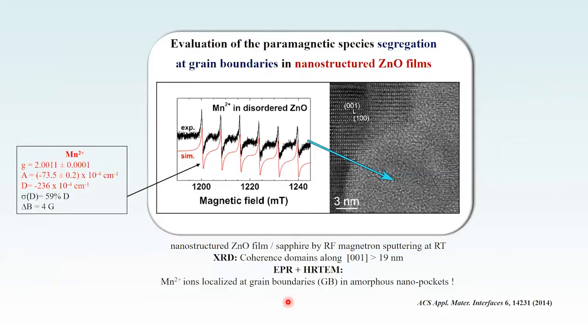This result was useful in investigating the properties of zinc oxide films. In an undoped film, we observe the presence of native manganese impurity ions at ppm concentration. From correlated EPR and high-resolution TEM, we concluded that the impurity ions were segregated in an amorphous environment. This is difficult to detect at such low concentration by other techniques. We can correlate these findings with electrical or magnetic properties which could change due to such impurity accumulation in the grain boundary areas.